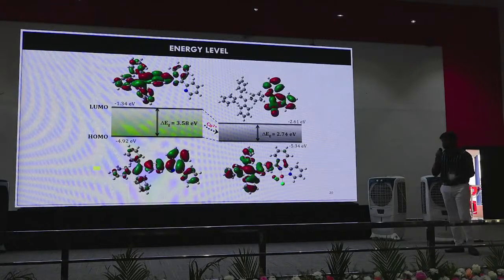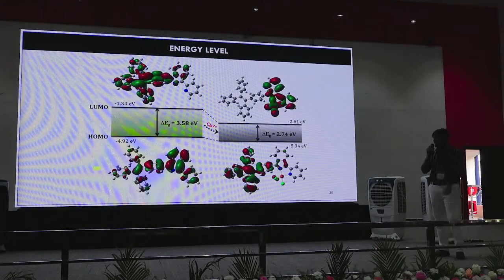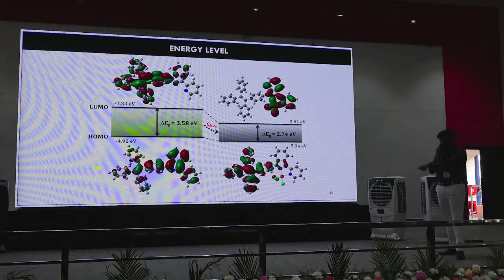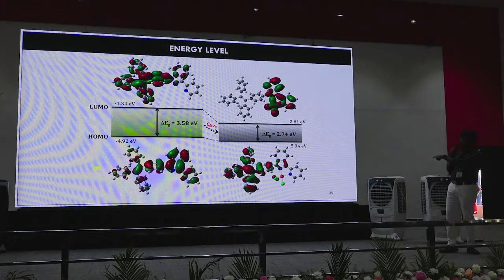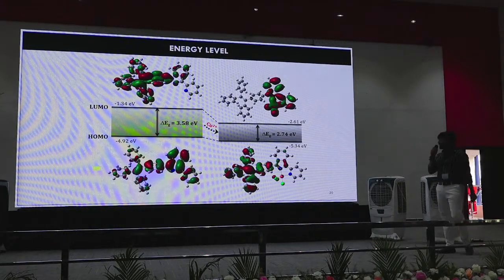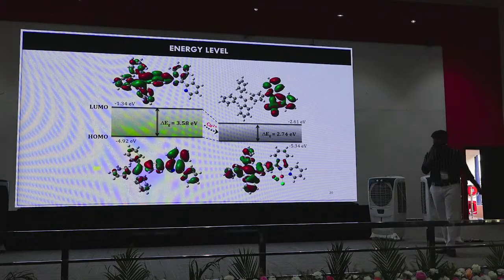And we also did the usual energy level diagram. As you can see, this is the HOMO-LUMO of the standalone TPE molecule, and this is after the introduction of copper, that is the analyte. As you can see, the energy difference between the HOMO and LUMO has drastically reduced. This is indicating that there occurred an electron or energy transfer from my probe to copper. That is the case of fluorescence quenching.